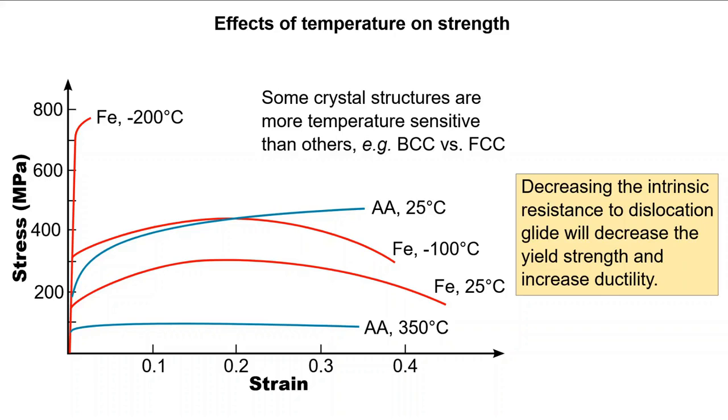Note that at the highest temperature for aluminium, the rate of work hardening is nearly linear, implying that it can be deformed indefinitely with relatively low stresses. Beyond the fact that there are two dramatically different underlying crystal structures whose baseline ductilities are different, the main reason for this type of behavior is that the resistance to dislocation movement diminishes dramatically as temperature increases, regardless of the metal and underlying crystal type. By the end of this lecture, you'll be able to appreciate why.